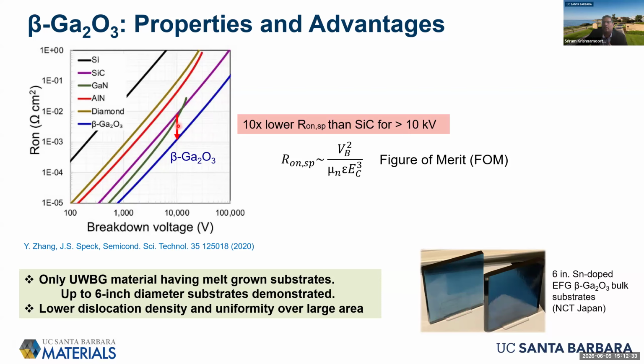If we make a back of the envelope calculation of the on resistance versus breakdown voltage trade-off for gallium oxide, we see that when you cross 10 kilovolts, it can in theory have 10 times lower on resistance than silicon carbide. So that makes it very exciting. At the lower voltages, gallium nitride and silicon carbide are already doing great. There's an ecosystem out there, and lots of exciting products are coming out. So we think for a new material like gallium oxide, the use case could be at a much higher voltage that is harder to access with the current materials.